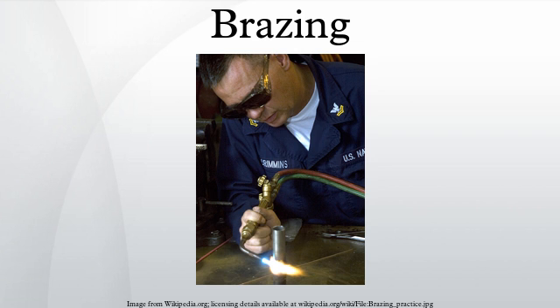Noble gas: non-oxidizing, more expensive than nitrogen. Inert. Parts must be very clean, gas must be pure. For copper, silver, nickel, copper phosphorus and copper zinc filler metals. For brazing copper, brass, nickel alloys, Monel, medium and high carbon steels, chromium alloys, titanium, zirconium, hafnium.